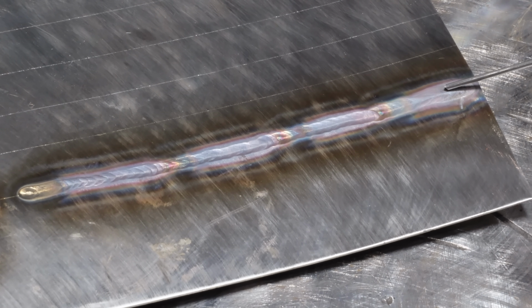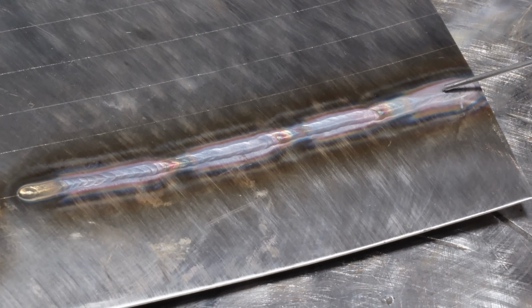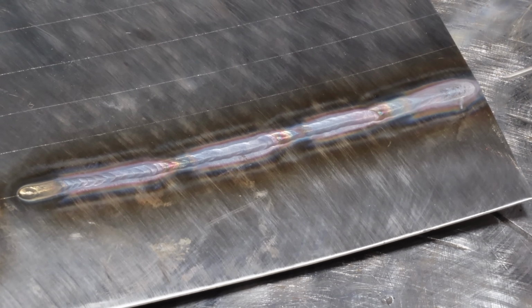One, the argon flow on the number 8 cup I was using was pretty low. It was around 17 or 18, so that's not doing any good. You should be up around 20 to 25, maybe even 30, depending on the cup and the gas lens. If you're using a collet body, this is probably about the best you can expect with a collet body number 8, and not really any better.